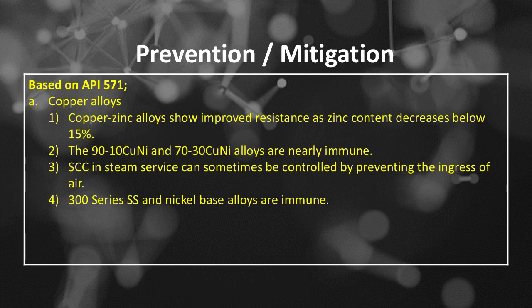Ammonia stress corrosion cracking damage prevention and mitigation based on API 571, number A, copper alloys, includes, number 1, copper-zinc alloys show improved resistance as zinc content decreases below 15%. Number 2, the 90-10 CuNi and 70-30 CuNi alloys are nearly immune. Number 3, SCC in steam service can sometimes be controlled by preventing the ingress of air. Number 4, 300 series SS and nickel-base alloys are immune.